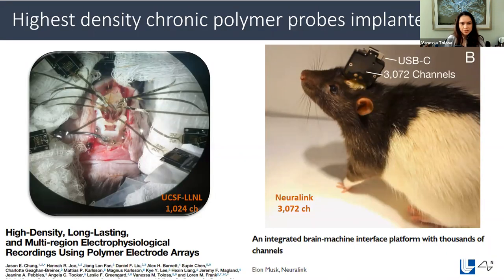And over the years, many researchers, including teams I've worked on, have been trying to validate this idea that microfabricated polymer probes could be an answer to getting us more data in and out of the brain in a chronic implantable way. Here are a couple of examples of projects where we were pushing those limits both in channel count and showing that we could record neurons for very long times, at least in rat lifetimes. This is work I did at Livermore with UCSF and also at Neuralink. At the time of publishing, as far as I know, these were the highest channel count polymer probe implants in rats.